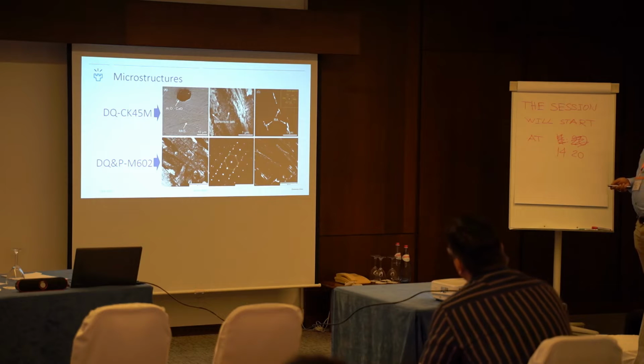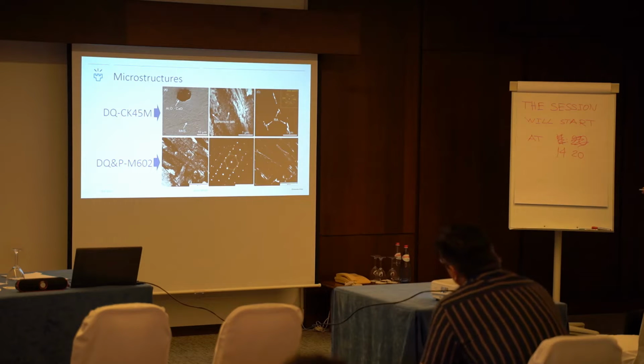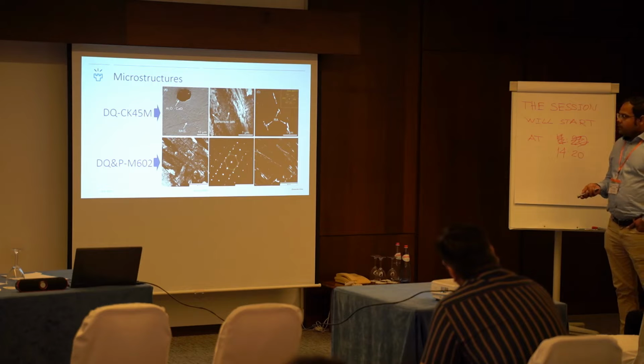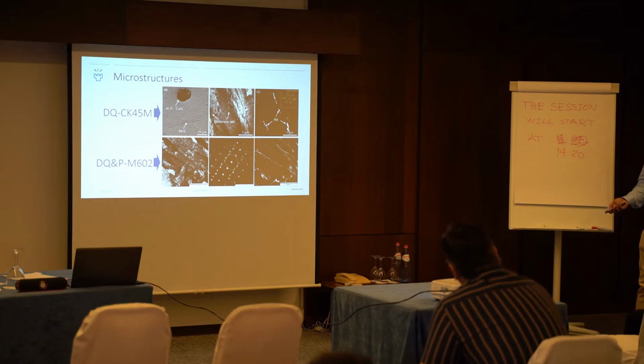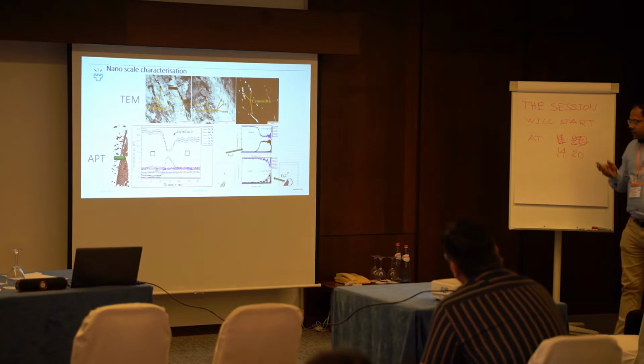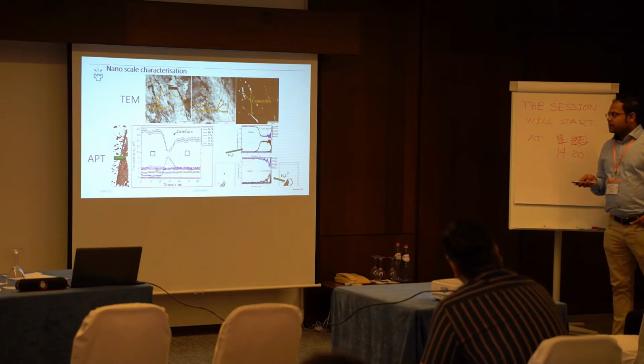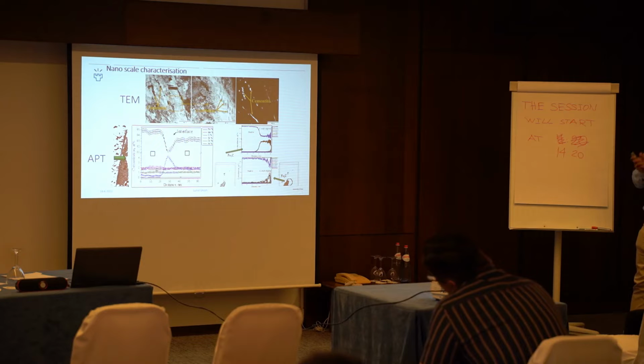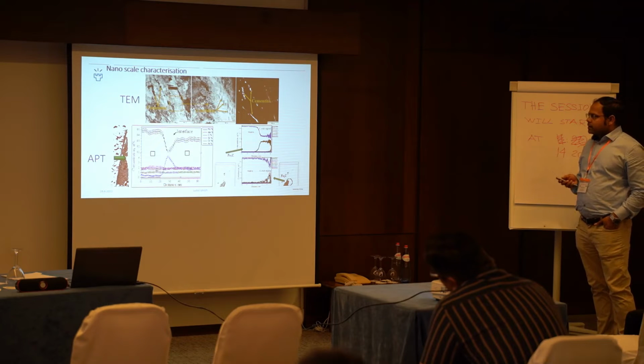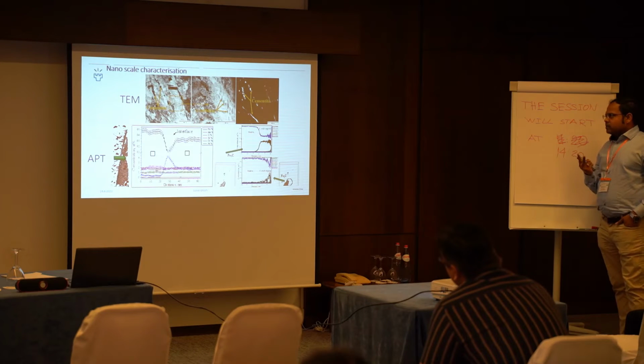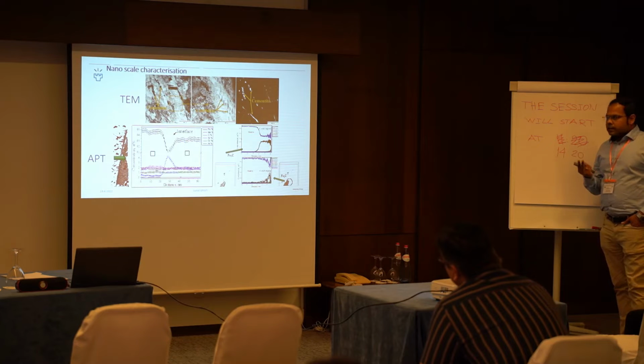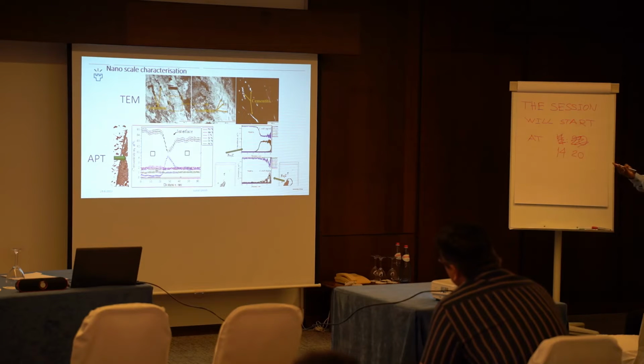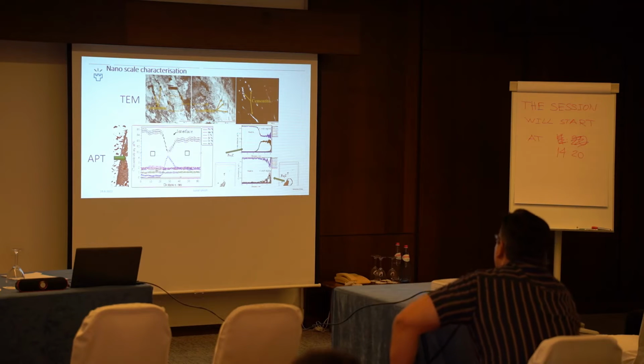And then in the case of DQ&P steel, we can see a high fraction of retained austenite present, mainly located at the interlath region. And then we investigated slightly more under TEM, and we observed two different kinds of precipitation occurred in this direct quench and partitioned steel. So based on TEM analysis, we identified there are mainly two types of precipitates. One is transition carbide, another one is cementite. Mainly it was transition carbide precipitate, and a few fractions of cementite are also present in the microstructure.